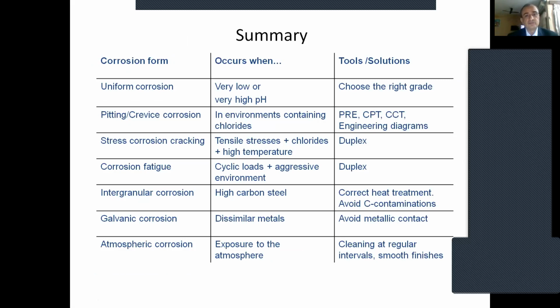Pitting and crevice corrosion occur in environments containing chlorides. Stress corrosion cracking is tensile stress plus chlorides plus high temperature. Corrosion fatigue is cyclic loads plus an aggressive environment. Intergranular corrosion is due to high carbon steel and an incorrect heat treatment process.